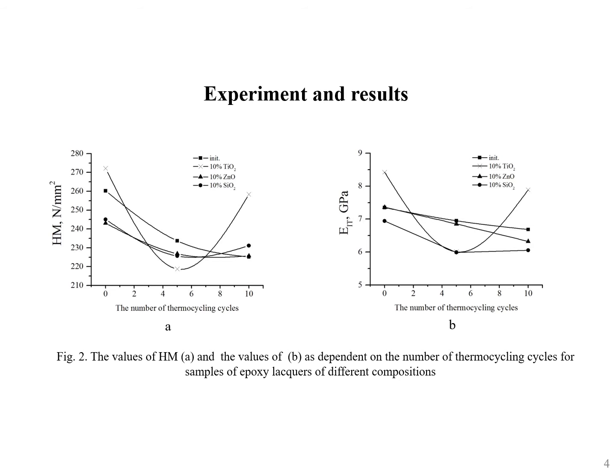For the coatings filled with zinc oxide, the value of the contact elastic modulus is 7.4 gigapascal, thus remaining on the level with the values for the pure epoxy lacquer. In turn, for the coating containing silicon dioxide, the value of the modulus decreases by 6% to become 6.9 gigapascal. Most likely, the obtained results are explained by the influence of the size of the filler particles and agglomerates. Namely, the smaller the size, the higher the elastic modulus.